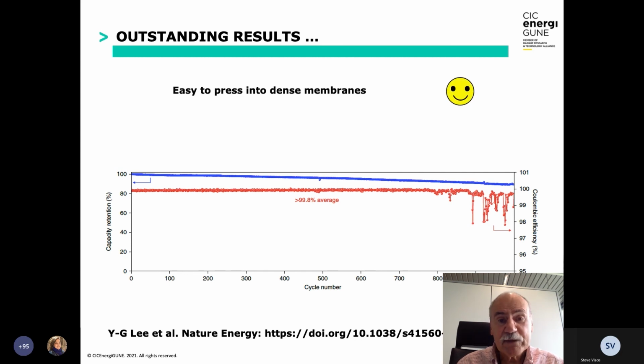And this material, the argyrodite and the sulfide in general, are easy to press into dense membrane. But they tend to be extremely sensitive to moisture and release H2S, which is highly toxic. So there is an advantage and a drawback.